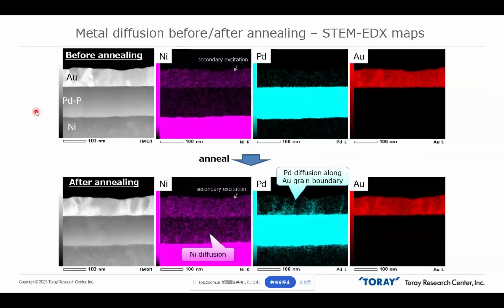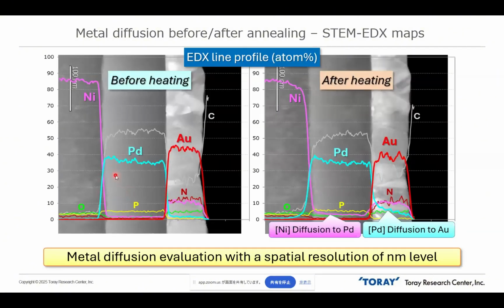The elemental composition distribution can also be examined by using the conventional STEM-EDX techniques before and after annealing. After annealing, we can confirm that nickel is diffused into the palladium layer, and palladium is also diffused into the gold layer. This metal diffusion can be confirmed in this line profile. So after heating, nickel is diffused to the palladium layer, and palladium is also diffused to the gold layer.